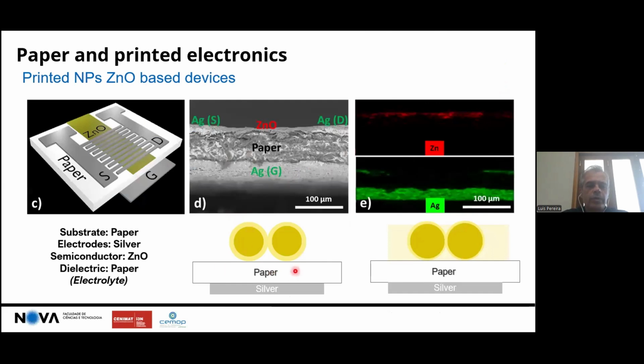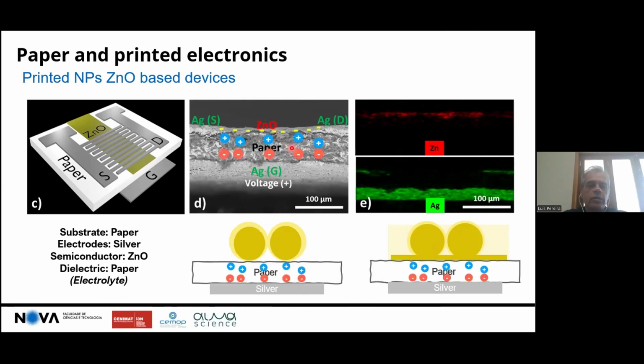And we tested on paper dielectrics, starting, at that time, from a conventional paper. And as I mentioned, you have the particles over the paper, and when you put this precursor, basically you create a layer that glues the particles to the substrate and keeps the particles together. And what happens is that the paper itself can work as an electrolyte, a very bad electrolyte, but it works as a solid-state electrolyte. And when you put a positive voltage at the gate, you displace ions, you create the electrical double layers, you accumulate electrons on the surface, on the interface between the paper and the particles. In this case, also in the film of the zinc oxide that results from the precursor, and you can create a channel. And you can also modulate the depletion layer that exists around the particles.